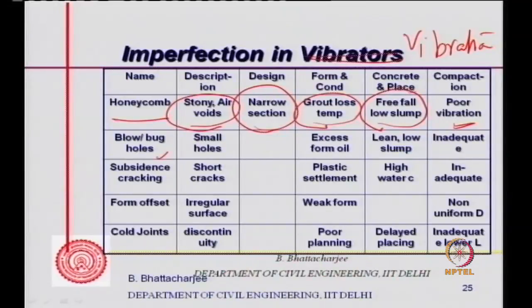Blow holes or bug holes, which you see normally in concrete, are small holes, aesthetically ugly looking. Excess form oil, if you are using it, can cause this, and so can lean and low slump concrete, and of course inadequate vibration. So poor vibration can result in honeycombing, and inadequate vibration can increase bug holes formation. Bug holes are pretty common. They are not very harmful, but they look very ugly. Not a good finish. Subsidence and cracking, of course, can happen due to plastic settlement.